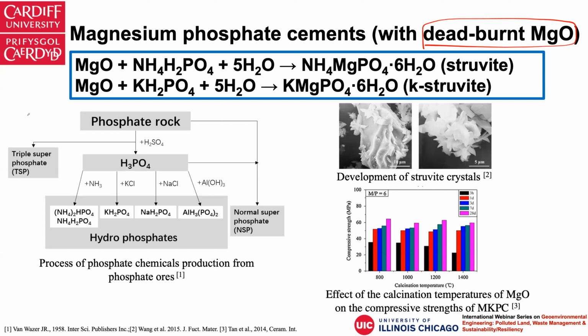That is because, if you look at these reactions, the acid-base reactions usually happen very fast, but are highly exothermic, so they emit lots of heat. So you need to control the reaction rate in order to slowly release the heat to gain the strength. So this reaction rate is controlled by using the dead burn magnesia instead of the reactive grade. But later you see in soil remediation, actually you can change the grade of the magnesia in order to suit your needs. And also you can change the reactivities of the phosphate phases as well. And later you see some examples.